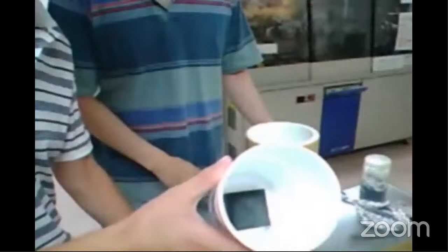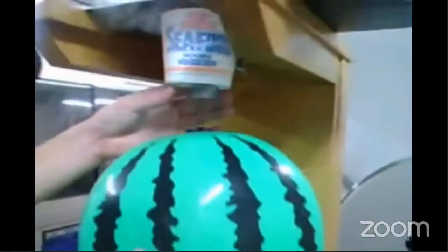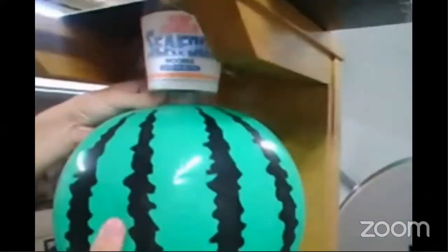But if we cool down this high TC cuprate by using liquid nitrogen, and also this cup is just like a cup noodle. We put the high TC in the cup noodle and cool down by using liquid nitrogen. Then the sample becomes the superconducting state. Then if we put on the magnet just underneath, okay? Underneath. So it's not connected, but high TC oxide can fish the material like that. So this is a fishing effect.